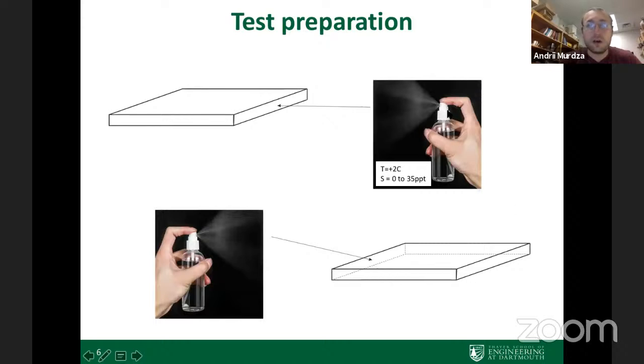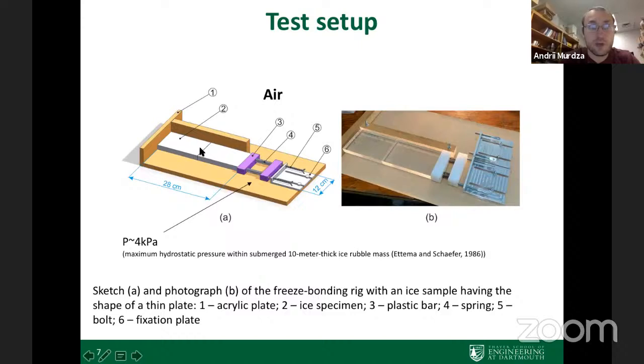Then the surfaces that were supposed to be brought into contact were sprayed with a fine mist of temperature 2 centigrade, and the salinity was varied from 0, meaning the fresh spray, up to 35 ppt, parts per thousand. Quickly after spraying, the surfaces were brought together, and on the left image you can see the schematic. These white parts are the two pieces of ice brought together, and we also injected a little bit of extra water with a syringe just to ensure that the surface of the bond is fully wet, and if there was any extra water, we would just wipe it off.